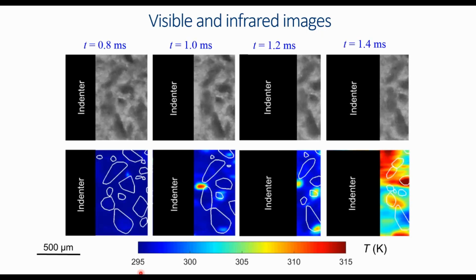Simultaneous visible and infrared images allow, for instance, locating those hotspots you can see here with respect to the microstructure features. Identification of the location of those hotspots can be very important in this case, for example, for understanding the mechanism underlying the formation of those hotspots. For example, a hotspot inside of a grain like this one, far from interfacial boundaries, most likely will result from inelastic deformation, while a hotspot at the boundary will likely result from frictional dissipation. And note again the temporal resolution here, which is 0.2 milliseconds, highlighting the need for very fast infrared cameras.